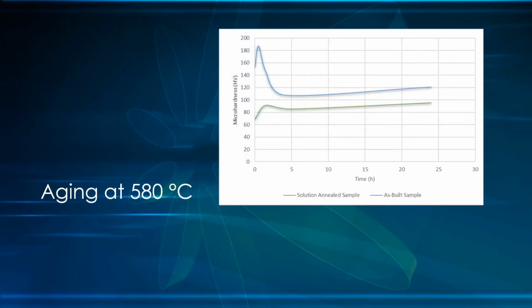So after that, we performed aging treatment at 580 degrees centigrade, and we performed this aging treatment on two types of specimens. One was the as-built specimen. The other one was the same specimen but after solution annealing, performed at 980 degrees centigrade.